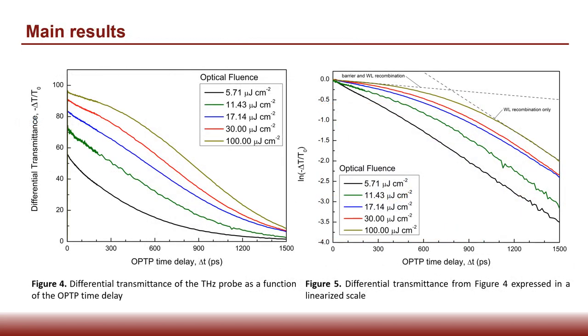Figure 4 shows the photogenerated carrier decay for the five optical pump fluences. These were linearized to extract carrier lifetimes, which is proportional to the slope of the curves in Figure 5, and shows a change in the dynamics at about 800 picoseconds.